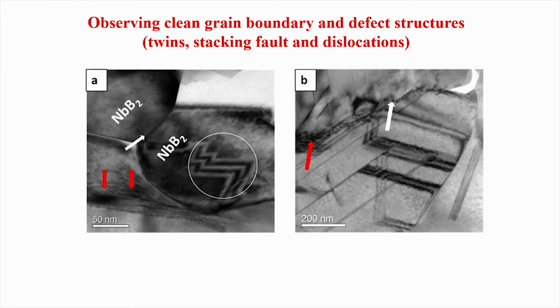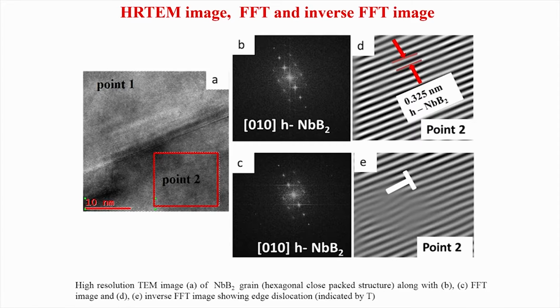Now, what you notice here is very clean grain boundaries. So, no grain boundary phases, which is also expected, and then we have seen the stacking faults and some twins, and these intersecting twins are observed in these materials. These are the kind of defect structures which we have very clearly observed in this niobium boride microstructure. This is the high resolution transmission electron microscopic image, and this one is essentially called a lattice fringe image.